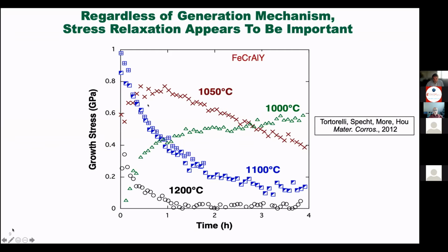But if you think about this, it's a very clear indication of some mechanism that's reducing the appearance of this stress during the earliest stages of oxidation. And again, I have to point out that because of the synchrotron radiation, we are able to get this data within 1 hour, whereas with a conventional X-ray source, you couldn't start taking data such as this until somewhere between 1 and 2 hours. So much of the action would have been missed using a conventional source.